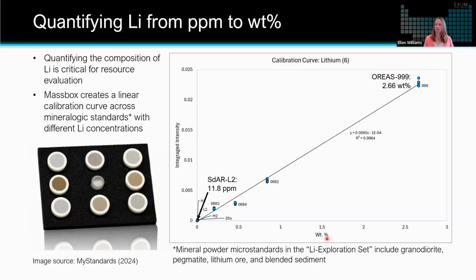And we see this nice linear response from our detector that gives us confidence that if we were to analyze an unknown rock or mineral sample with some amount of lithium from 12 parts per million to 2.5 weight percent, we could plot it on this curve and determine how much lithium is in that sample. So this just shows you how we get quantitative data out of the mass spec that we acquire on an unknown sample. And it gives you a sense of how we approach analyzing an unknown material.